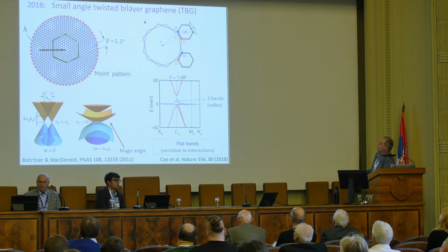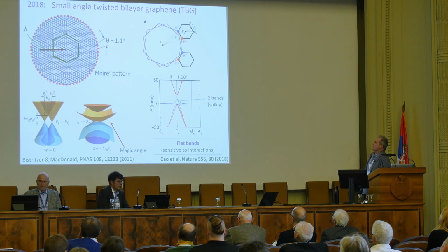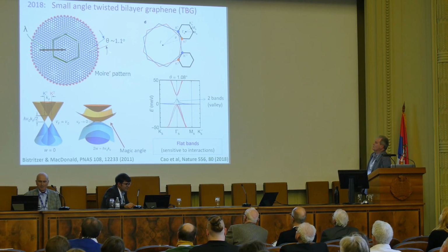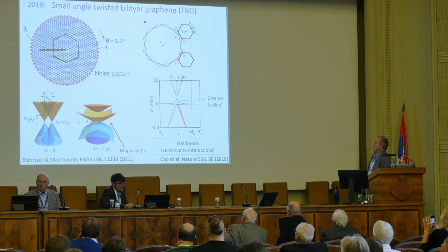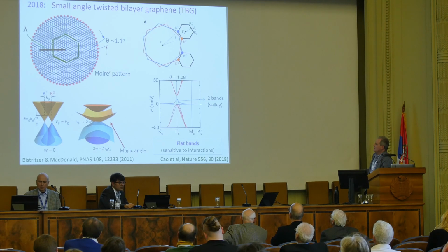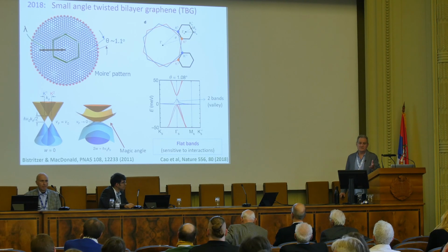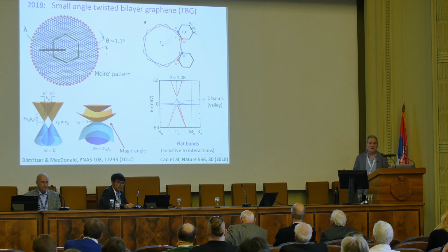graphene and you rotate them, you get this moire pattern. And what you're doing, because graphene is a Dirac semimetal, is that you are moving the two Dirac cones slightly away from each other and giving you a Brillouin zone, which looks something like this, a very small Brillouin zone. And ultimately, if you twist at just the right angle, you can get a band structure which has a very, very narrow band, nearly separated from the other bands in the system. Now, flat bands are high density of states. High density of states is good for superconductivity. So even naively, if there were a pairing interaction around, this would be a good thing for a superconductor.